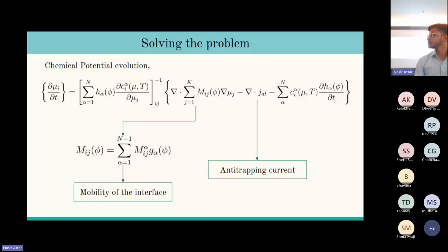So then you actually introduce a problem of solute trapping, which means the equilibrium composition of the solute starts to become much more different than what in reality, in the experiment, it would be, just because you chose the interface to be very much larger. So this is artificial. Remember, solute trapping does happen in physical experiments, but at much larger speeds, during rapid solidification. When your interface is moving that fast, the solute transport doesn't have time to complete, and your equilibrium composition changes. But here, because of the choice of a larger interface, you will start to have solute trapping at much lower velocity, where in reality, in experiments, you don't get it.